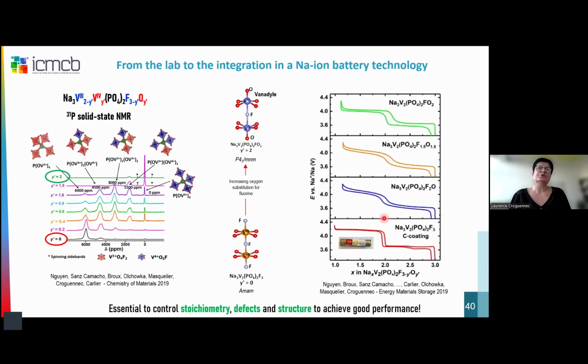So here I wanted also to highlight that here also the solid state chemists play a big role in the development of these materials because you can see that in the literature we had all that kind of electrochemical signature, and I would say even more this kind of electrochemical signature for the material I will call NVPF in the following. You can see that in fact, here we have very different content in oxygen and fluorine in these materials, and that this signature is really the one of Na3V2(PO4)2F3, so only fluorine here.